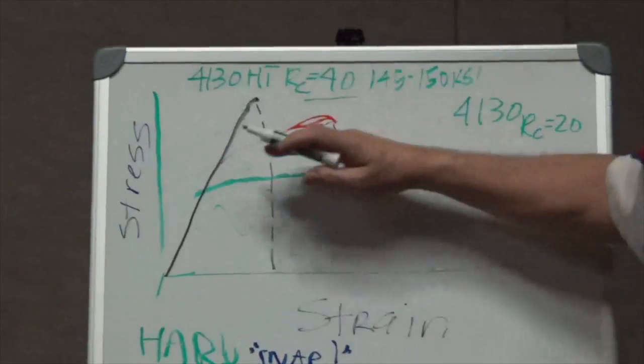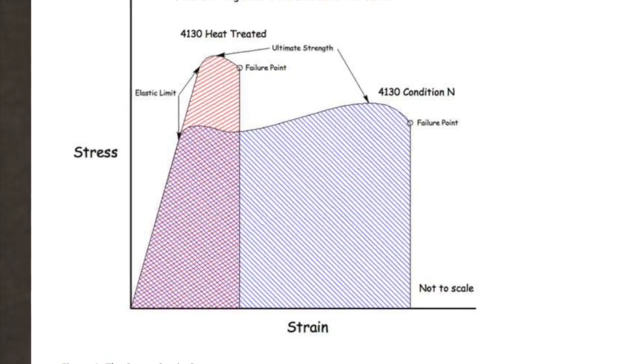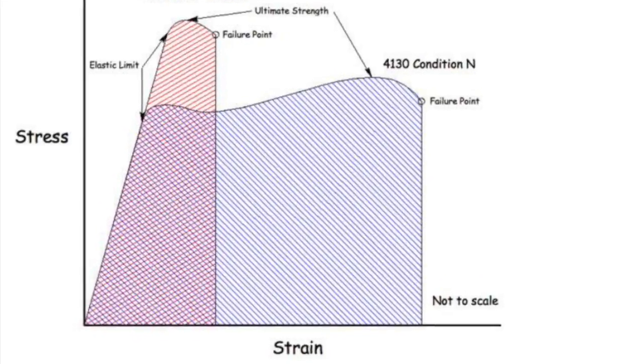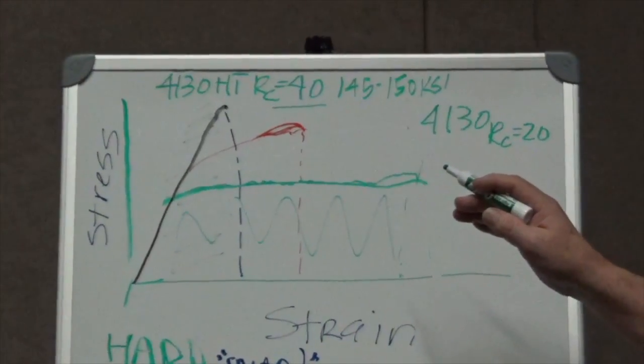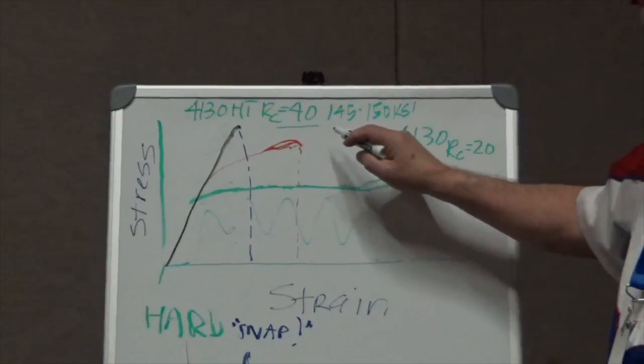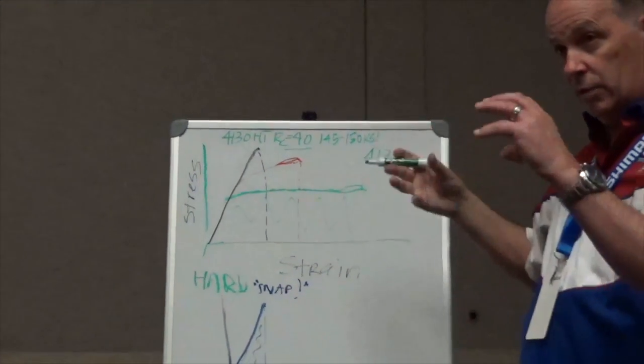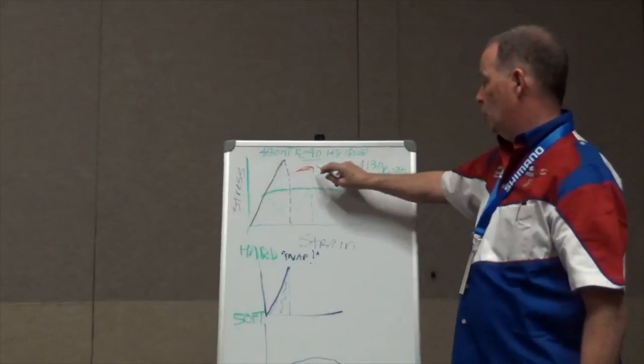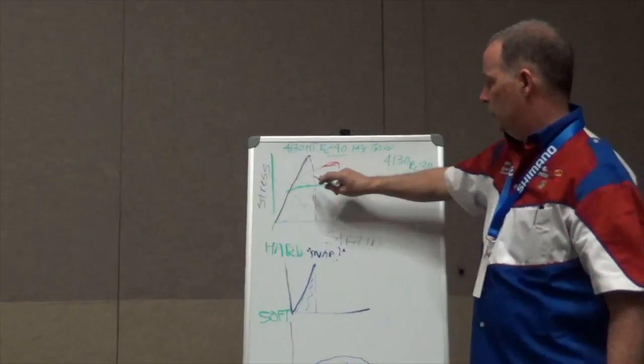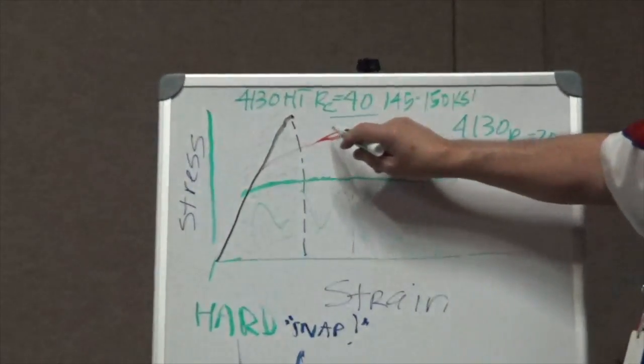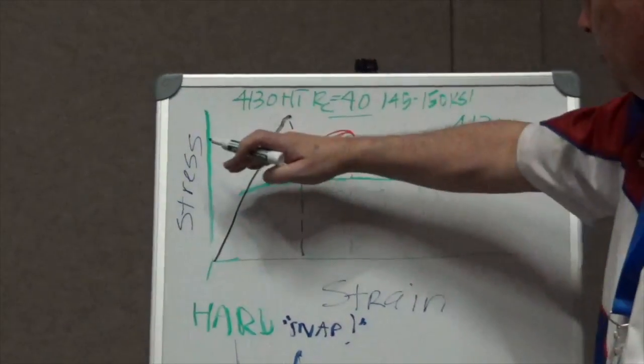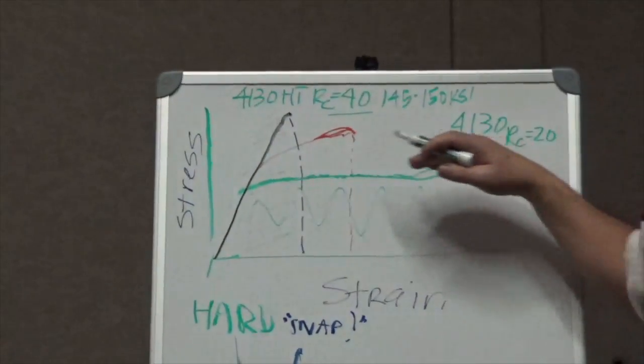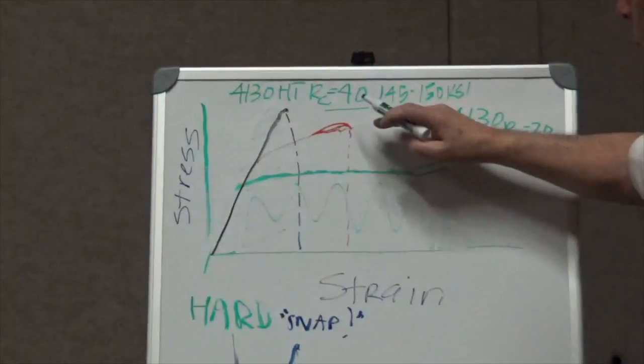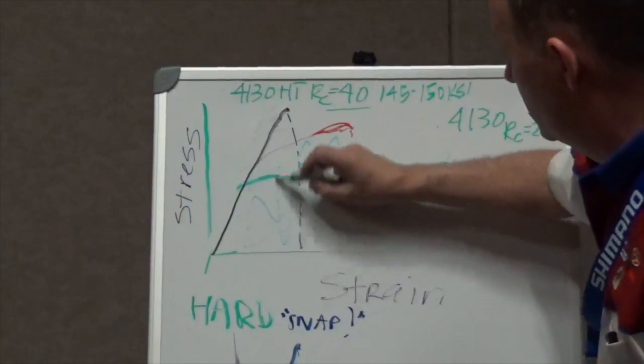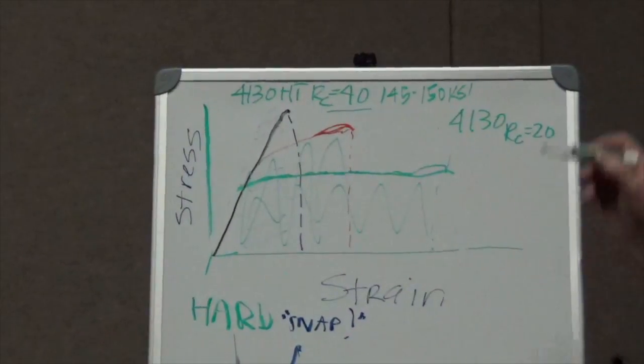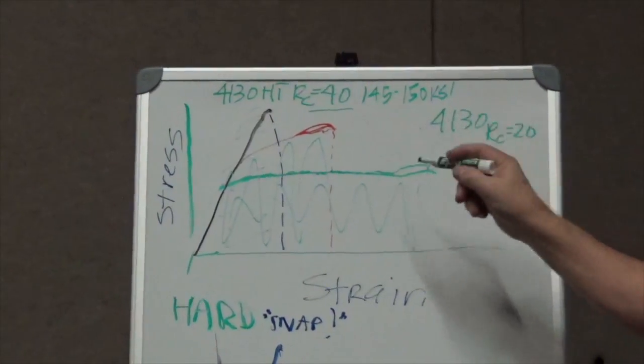Well, the truth is this graph probably needs to be a little bit lower, but what I want to show here is that neither one of these are optimal. They're both less than the material could be. So what you want to do in making tubes for bicycles, because of the geometry of bikes and how they're welded, is you want to find a way to make a material that will fail a little bit higher, but still have some of this. This distance is the ductility of the material. So what you're trying to do is optimize this so that whatever this area is, it's the highest. And that's the optimal way of making tubing for bicycles.